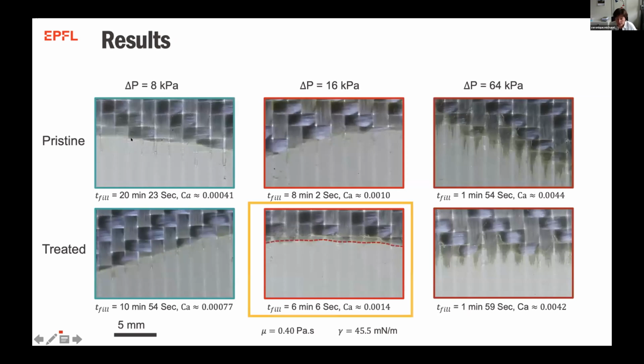And you see that, okay, at a capillary number equal to 0.0014, so quite slow, and a filling time of 6 minutes to get to this position, I have something that looks like a very uniform flow front. And that was for the treated fabric. Now, if I look at the pristine fabric, I'm not at the uniform flow front here, but I see that there is some lag behind.